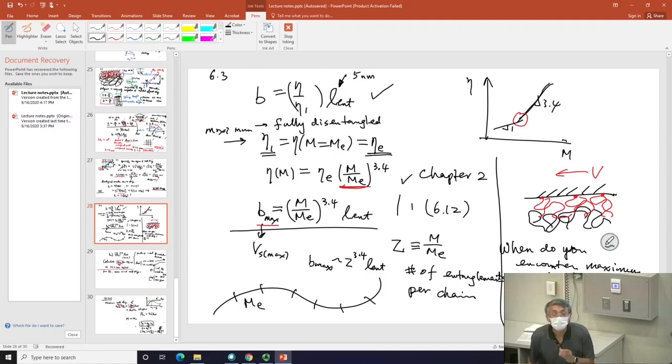But it's useful to know what is the maximum possible. When you have fully disentangled, as I described in detail already here, in that limit, there's something very explicit you can talk about. And certainly in the case if it's monodispersed, it's very explicit in terms of saying how it depends on molecular weight. Good point, yeah. So this expression here would not work so well if it's polydispersed. Because what molecular weight are you speaking about, right? Yeah. Okay.